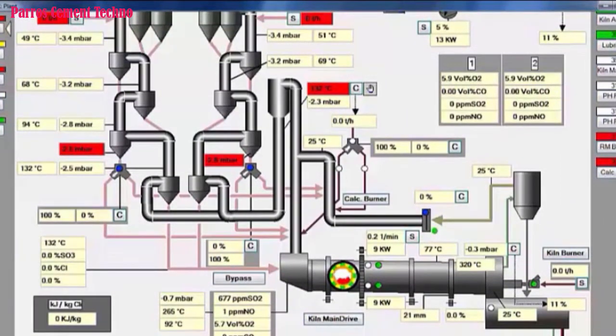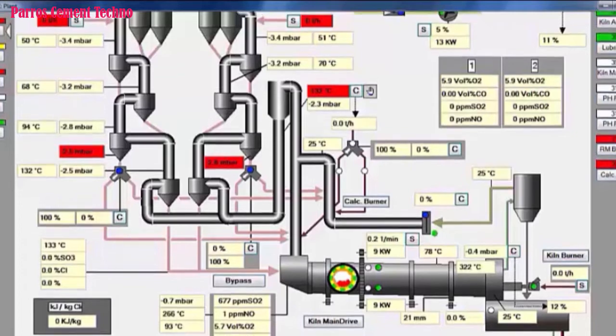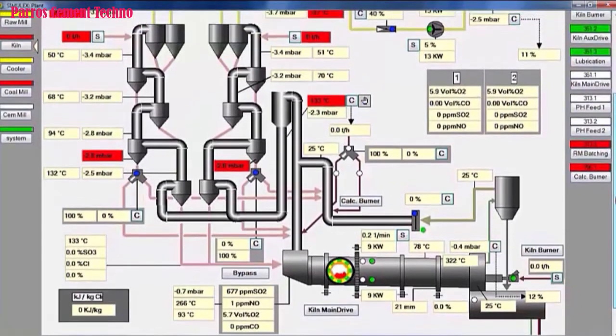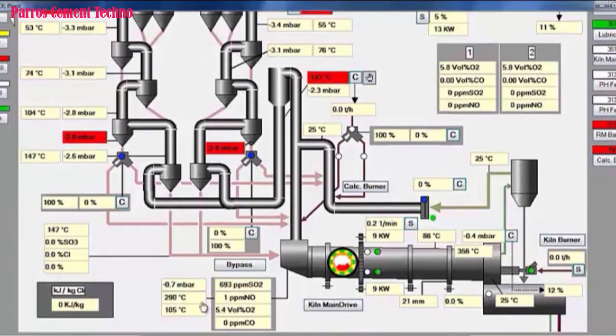Then at the 6th hour we will mix it with coal fuel. For mixing coal, the temperature in the sintering zone should be around 550 degrees Celsius, so that the coal can burn completely. The current kiln inlet temperature is 290 degrees Celsius and the sintering zone is 360 degrees Celsius.